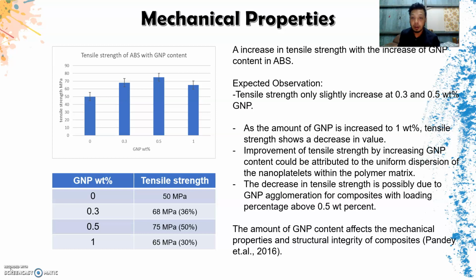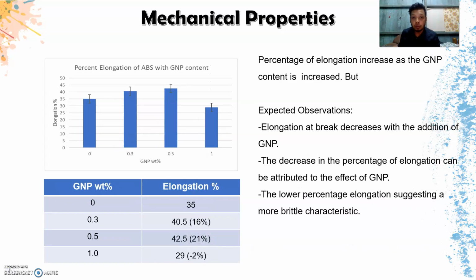The improvement of tensile strength with increased GNP content can be attributed to the uniform dispersion of the nanoplate within the polymer matrix, and the decrease in tensile strength is possibly due to GNP agglomeration for composites with loading percentage above 0.5 weight%. Next, we go to the expected result for percentage elongation.